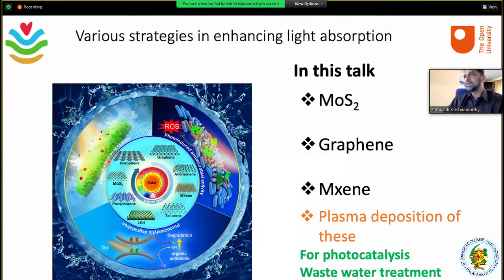Okay, and this can be used for photo-induced antimicrobial activities, and then photothermal evaporation, and finally photodegradation activities. So where you shine light and then you produce excitons. Excitons are the electron-hole pair. Okay, so you shine light and kick the electron out of the surface. Okay, and this forms a hole, core hole. And the electron is just going into the unoccupied density of states and forming a pair, an electron-hole pair. And this pair can rotate and finally quench, releasing light. And that is important in reducing the organic radicals or pollutants, and then that